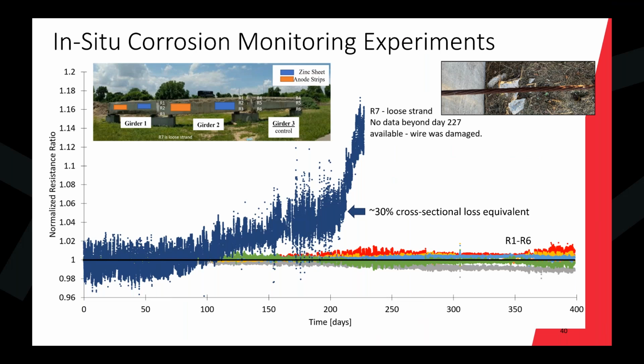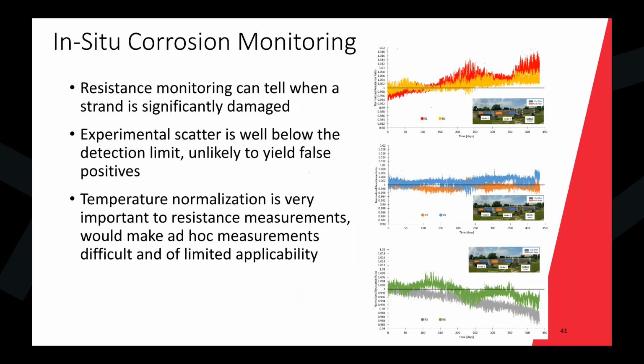But it did give us some really critical data, since we were running this experiment over would this be a viable technique to use to try and determine if strands are disconnected or not. Could I make a resistivity measurement across the strand and guess what the state was? And what we figured out is you can definitely tell when a strand is significantly damaged here. And there's some scatter, as a lot of this is post-process data. We've had to deal with temperature.